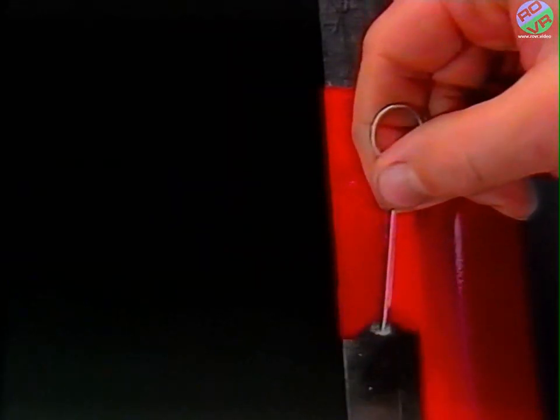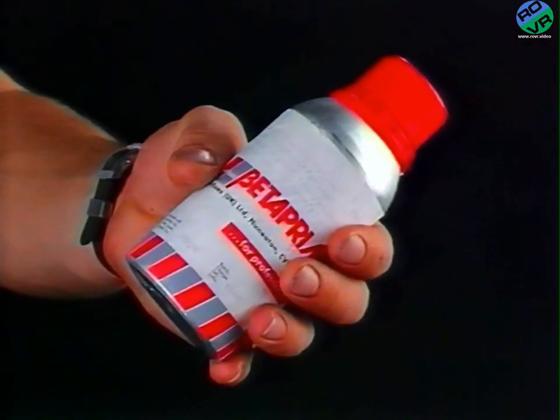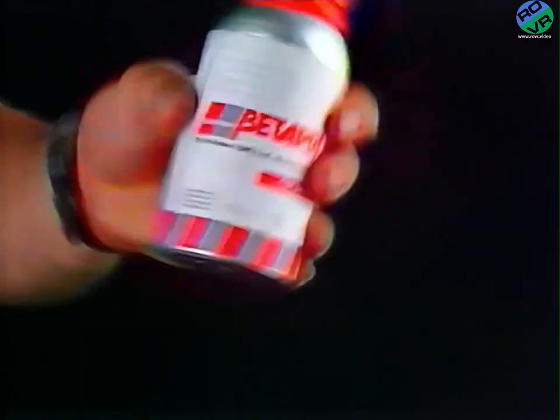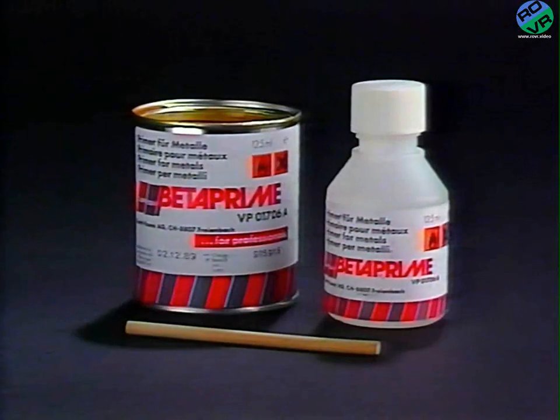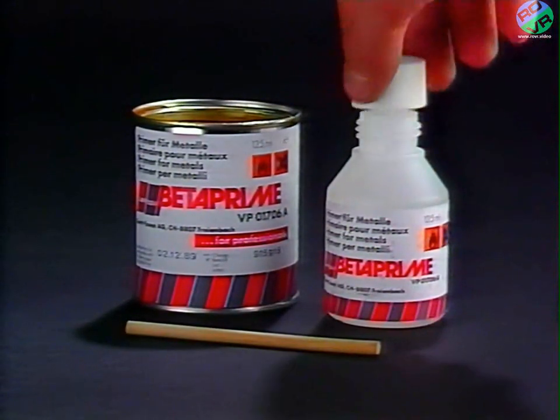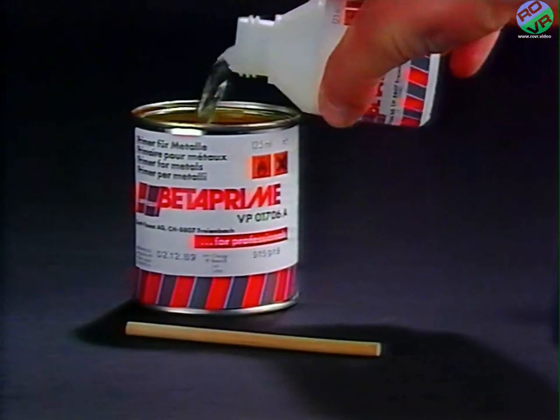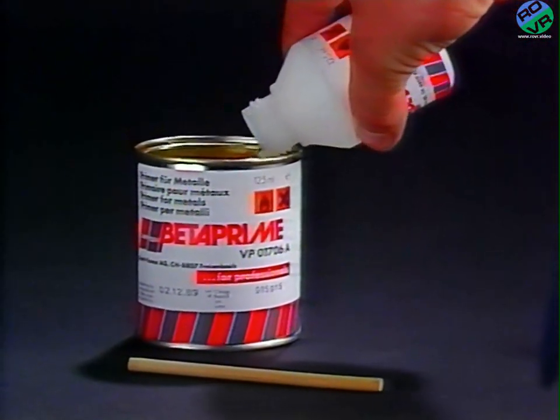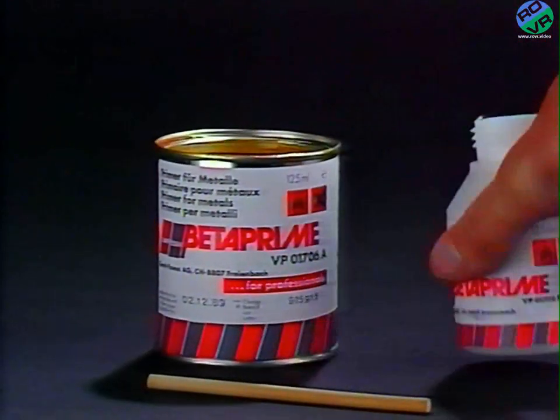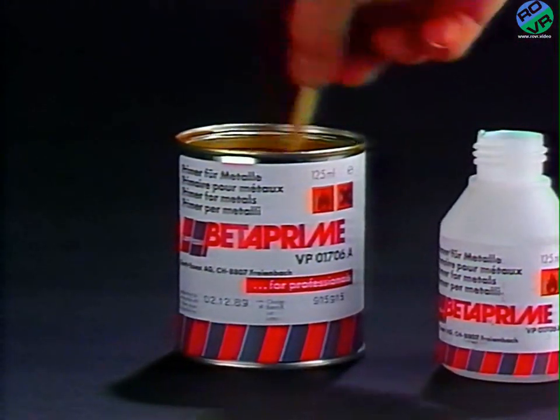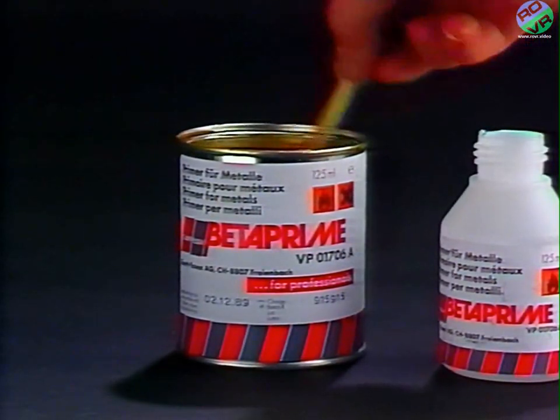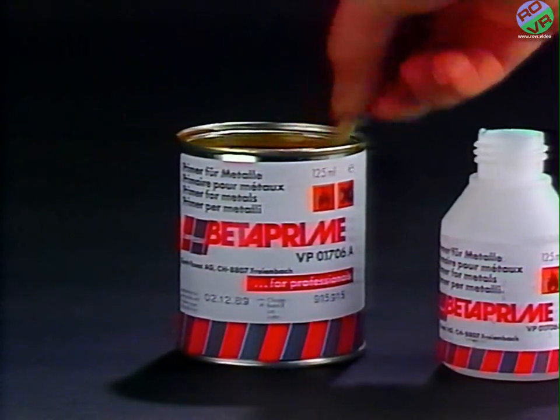So on sound paint, use the body primer 5402, the red cap. But remember, you must shake it for a full minute before use. And on cleaned bare metal, use the two-part 1706 A+B anti-corrosive primer. Product A in the tin should be well stirred. Then product B is added and the two thoroughly mixed in equal parts. The mixture must be allowed to stand for several minutes before use. The correct use of this product is essential to preserve the automotive manufacturer's anti-corrosion warranty. We'll show you how to apply it later.